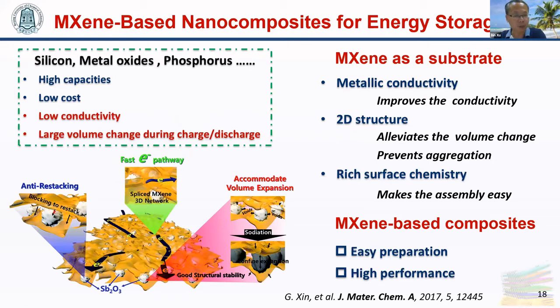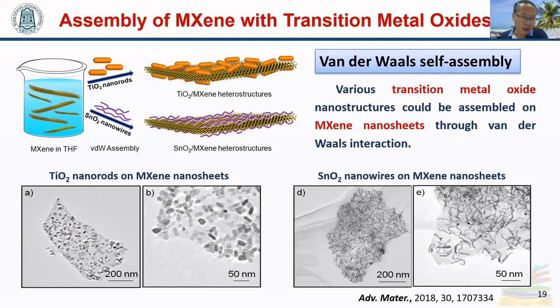MXene can help to solve these problems by acting as a substrate. Because MXene has metallic conductivity, it can improve the conductivity of the composites. The 2D structure can alleviate the volume change and prevents aggregation of the active materials. The rich surface chemistry makes the assembly very easy. So MXene-based composites is an effective method to develop advanced anode materials for batteries. I will introduce 3 strategies.